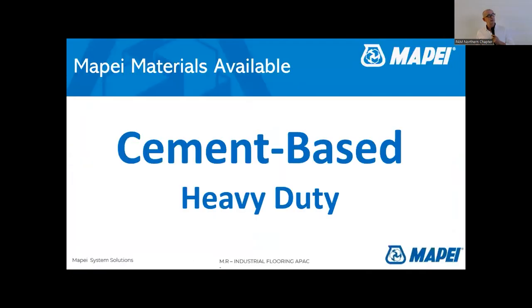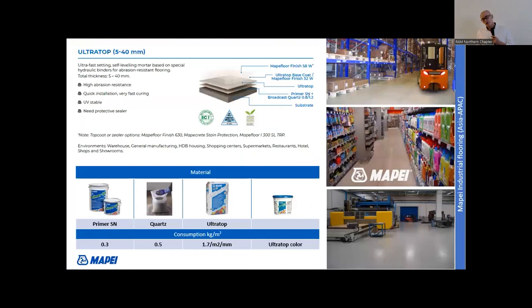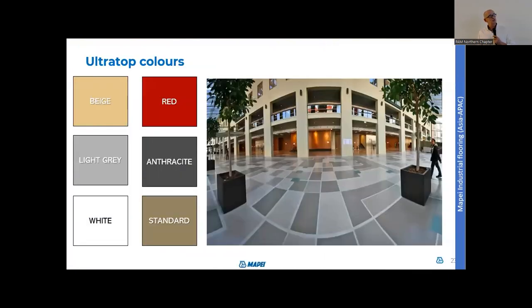Yeah. So different colors available. Cement-based heavy duty, the same cement family called Ultra Top. It's a minimum 5 millimeter self-leveling application. We use this in many areas, convention centers, heavy duty mall areas. We can apply this material usually in the range for this kind of project for around 8 to 10 millimeter. This material cures in 4 hours under heat situation between Singapore and Malaysia.